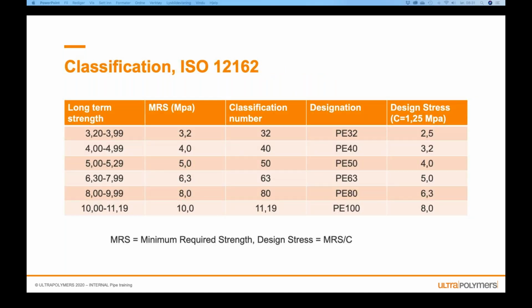For the ISO 12162, you can see here you have the minimum required strength. This is what we talked about at the hoop curves. So if you have 8, you have a classification number of 80. That means that you get a PE80. But when you design your product, you use 6.3. So that is only the minimum required strength divided by 1.25. And the same if you have a PE100, you design the product with a stress of 8.